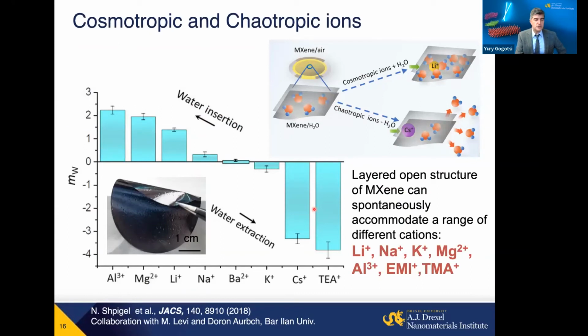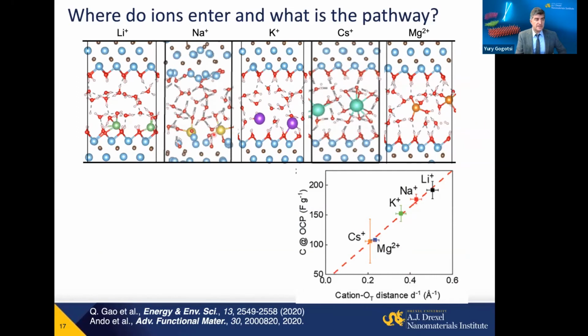Some ions can actually remove solvent like water from the layers. We need to understand this as well, what happens with MXene films. Now, even if you use aqueous solution and we try to develop aqueous batteries, we don't have organic toxic solvents, which can work under even an open environment, as long as no drying happening here, and which will be non-flammable.